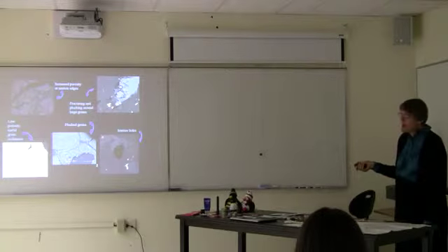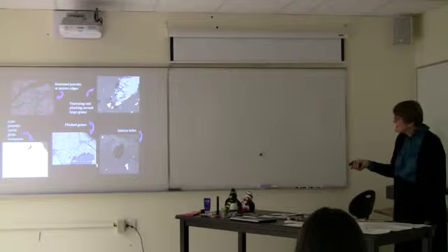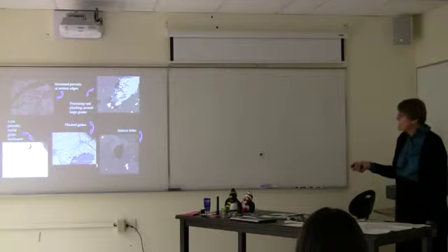This is full of epoxy. And I've learned you have to count the holes that are full of epoxy. And recently I've been doing some work where I found places that look like this. You can see the base of the thin section. And so it's something that's been plucked out of there, but I find places where you can see the epoxy starting to fill in this area, but then it just kind of quits in the middle.